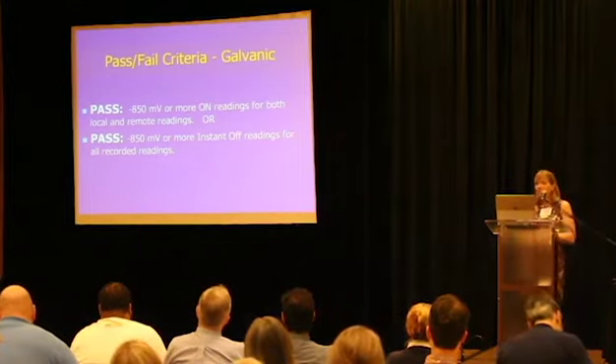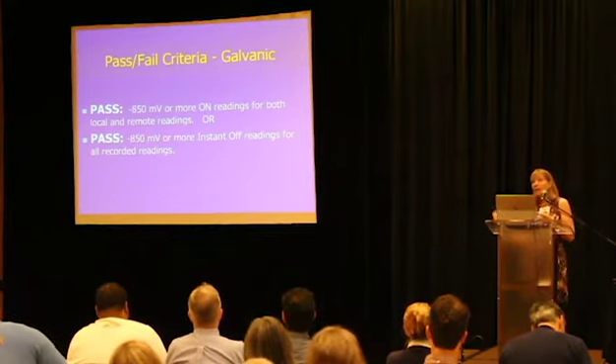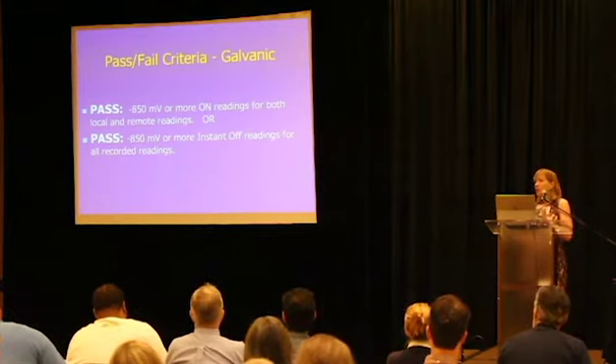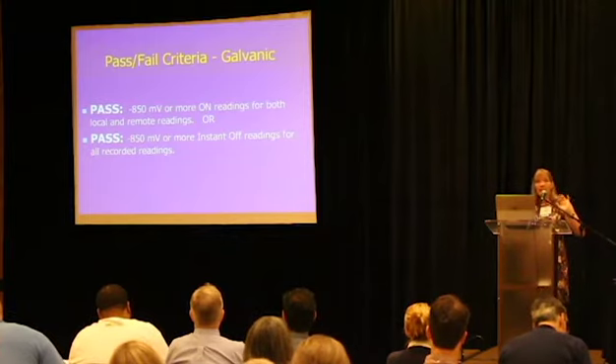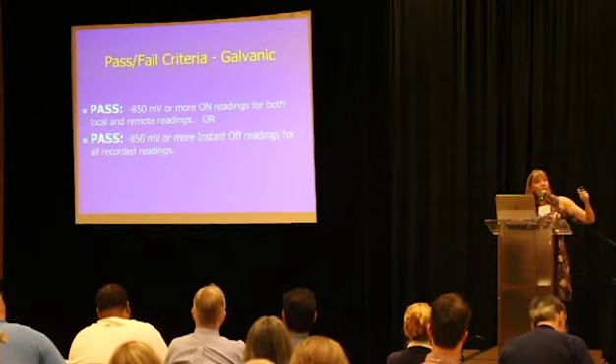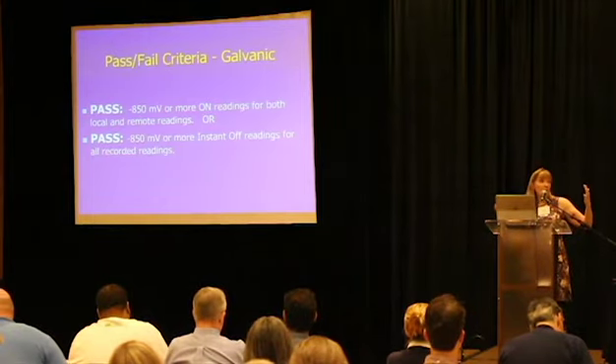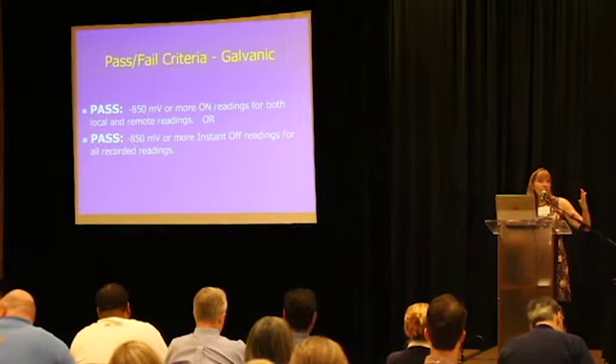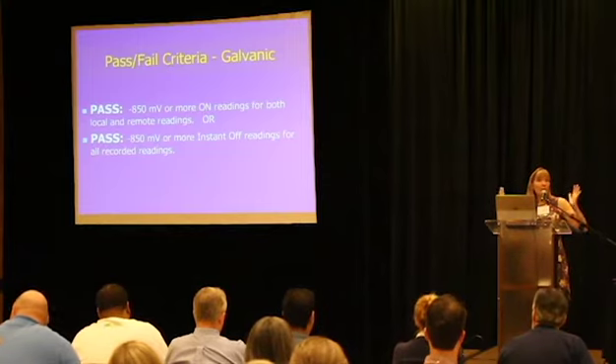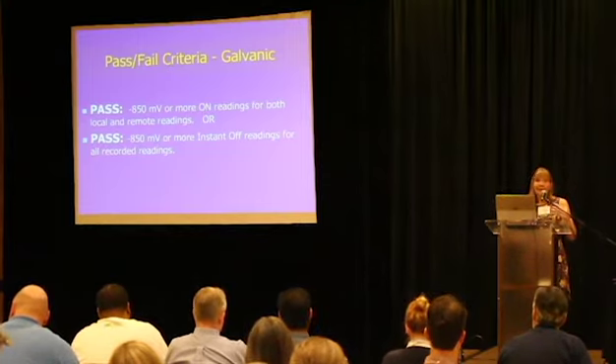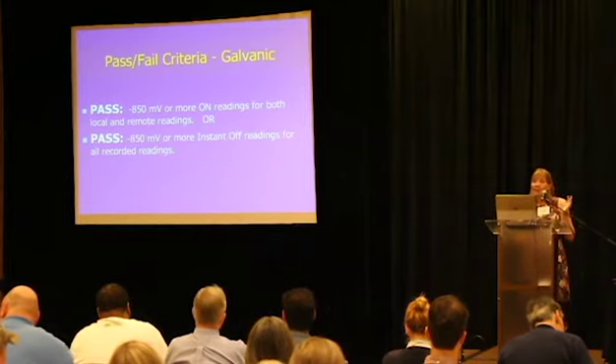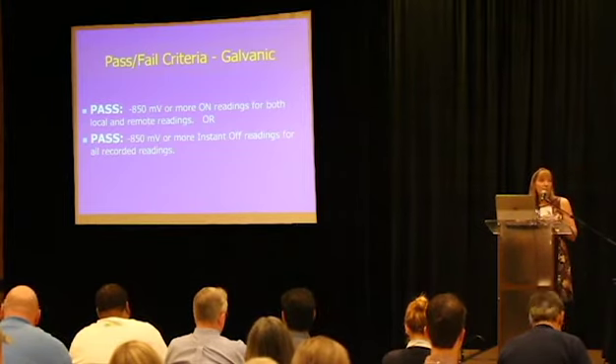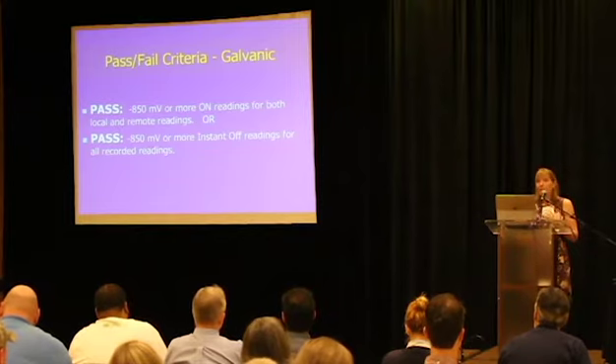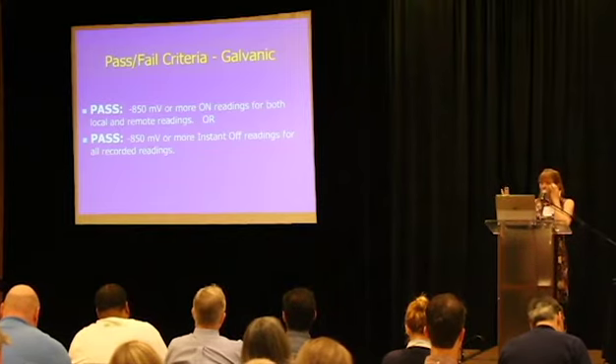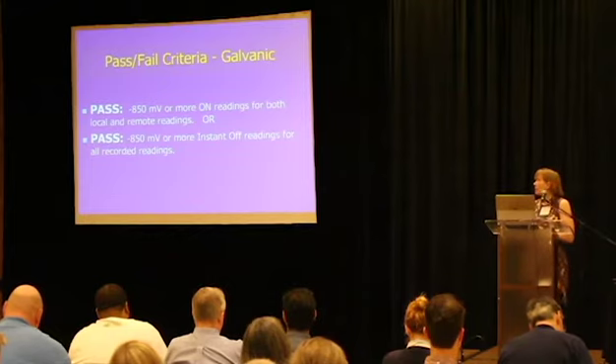Typically for a galvanic system, we're going to be using on readings, and an on reading just means that the cathodic protection is on. It's not turned off. On an impressed current system, that's really easy to do. You go and you flip the switch, the system's off. On a galvanic system, particularly an STI P3, where the anodes are welded to the tank, you're not going to disconnect anything. I mean, it's on. It's on all the time. And so we've taken a lot of readings, and we've proven that using those on readings is acceptable.